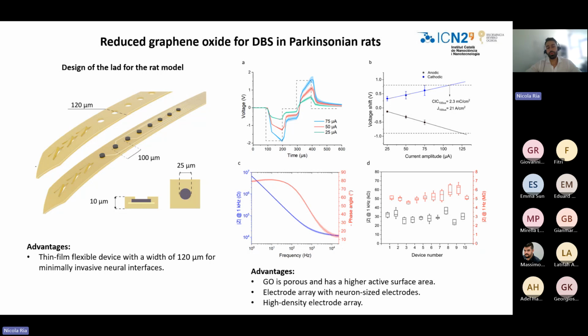The average impedance spectrum also shows good values, so capacitive behavior at low frequency and low resistive behavior at high frequency. And in subpanel D, we have also some extracted values for 10 different arrays, with the impedance at 1 Hz and at 1 kHz. So the fact that these electrodes can perform in this way allows for the miniaturization of the electrodes. Because even if the electrodes are very small, like 25 micrometers, so the size of single neurons, they can still deliver high charge density to reach the neuromodulation threshold of the tissue, and at the same time are able to record with low noise, so high signal to noise ratio.